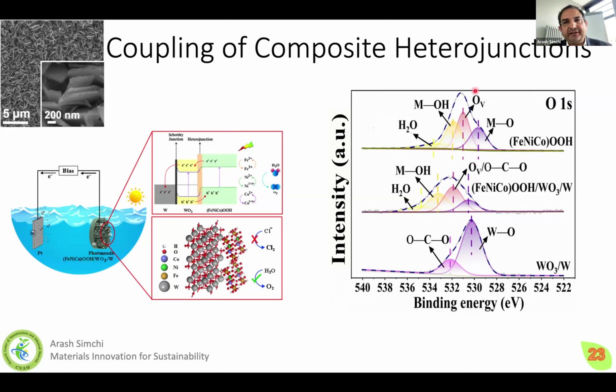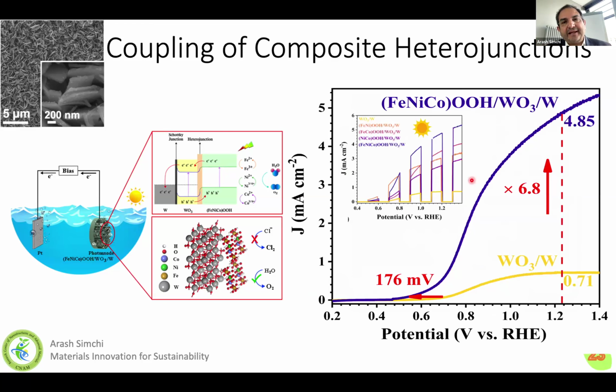As you see here, again, we create a lot of oxygen vacancies in the XPS data, and we show that there is a coupling between electrocatalysts, because if there is no hybridization or coupling between different layers, then the current doesn't pass through. Here is an example of our test when we used simulated sun. Here, when we have dark and we irradiate the sun, you clearly see the JV changes. What does it mean? It means that when we do not irradiate light on the catalyst, it doesn't work. As soon as we start to illuminate the catalyst with the sunlight, it starts to dissociate water.